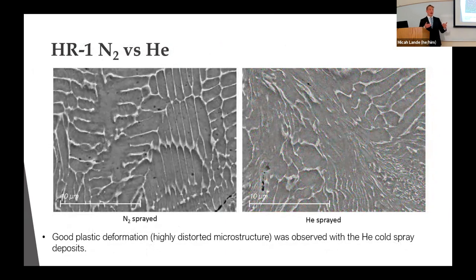So then going on to looking at actual cold spray solids, these are a couple of interesting, very close-up views of nitrogen and helium sprayed HR1, where you can see a pretty distinct difference in the plastic deformation for our helium sprayed, where things are much more stretched out and elongated versus the nitrogen sprayed. That shows that for our helium carrier gas, we're getting very good deposition, and it's also creating a better metallic structure, which also shows up when we get into mechanical properties.